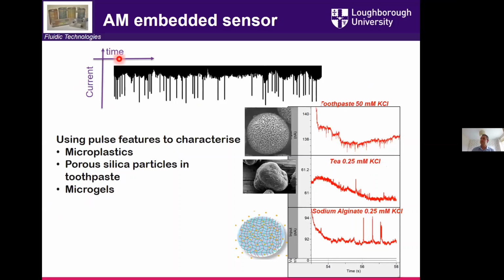And this gives you a feel for some of the benefits of resistive pulse sensing. You're measuring typically current versus time in the resistive pulse experiment. And the resistive pulse says that as a particle sits in the sensing region, it blocks some of the surrounding buffer, and the sensor sees an increase in resistance. It blocks the current, you see a decrease in current, and that's what all of these resistive pulses are. But depending on the material that you put in, if, for example, it is highly porous and has a diffuse double layer or a large amount of electrolyte with it, or if the material itself is conductive relative to the surrounding solution, you don't get resistive pulses, you actually get conductive pulses. So an example is when you're looking at hydrogels that have a higher conductivity because they're loaded with ions and drugs. You don't see the resistive pulses, you see the conductive pulses, and you get an inherently different signal depending on their physical properties. And it's that extra combination that we're looking to bring to bear for this.